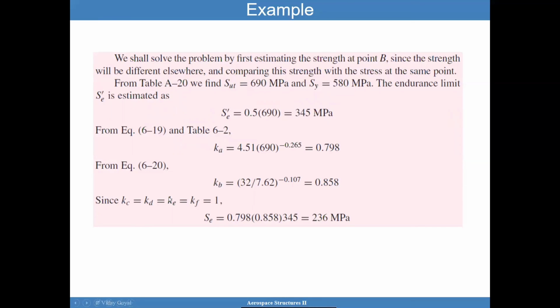In this case, Kc, Kd, Ke, and Kf are equal to 1, so no effects there. But you have that 0.5 that plays a role. The surface factor does play a role, and then the size factor plays a role. But other than that, you have reduced the Se prime, you reduce it all the way to Se after applying the Marin factors. And you drop from 345 to 236.